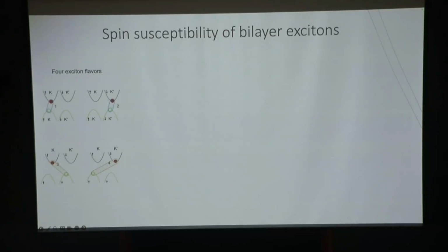At low energy, there are actually four different exciton flavors that are possible, because the electron and hole can each be either spin up or spin down. So there are four different pairings. And because spin and valley are locked, they also correspond to specific valley behavior. You have these so-called intra-valley excitons, where the electron and hole are both in the same valley, K or K prime. Or you can have these inter-valley excitons.